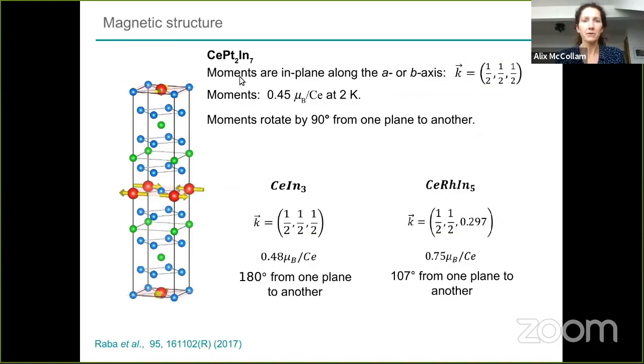The magnetic structures are also similar. So cerium platinum-2 indium-7: the moments are in the plane. They're sketched here. This is from Matthias Raber. They're about 0.45, or half, the Bohr magneton per cerium at 2 Kelvin. And the moments rotate by 90 degrees from one plane to the next plane.